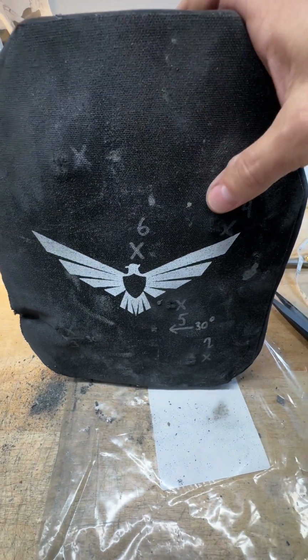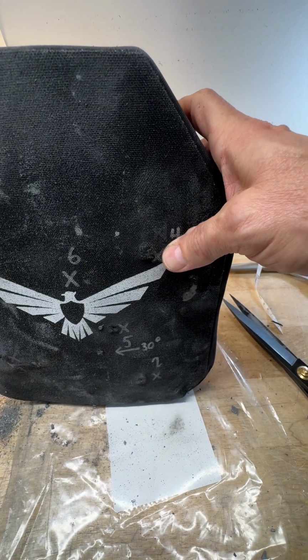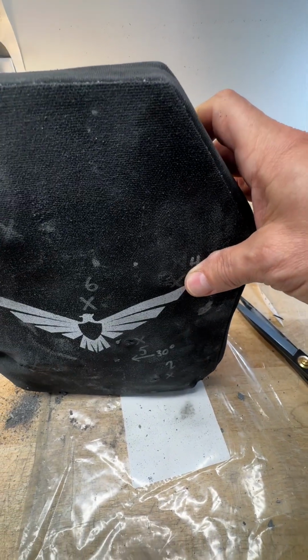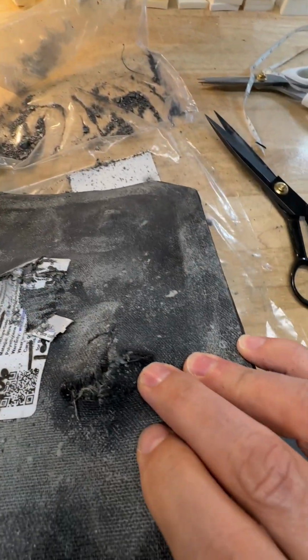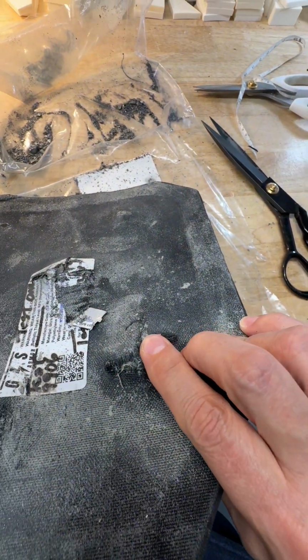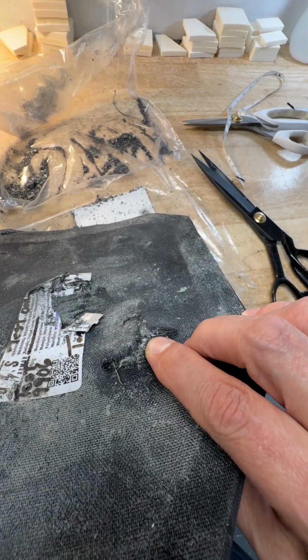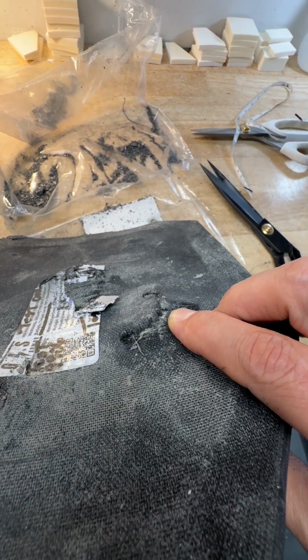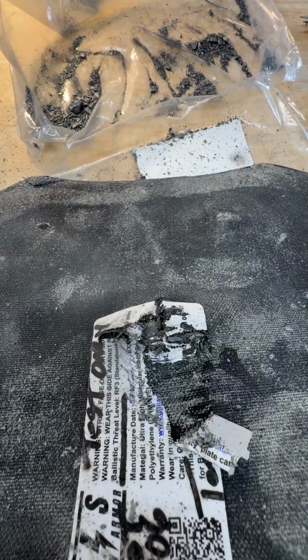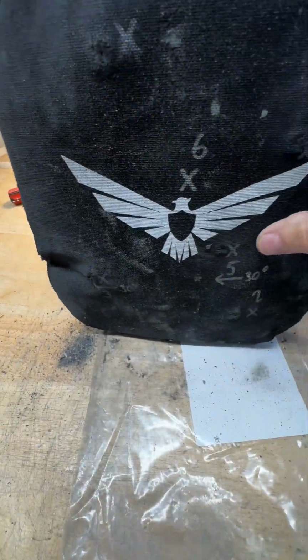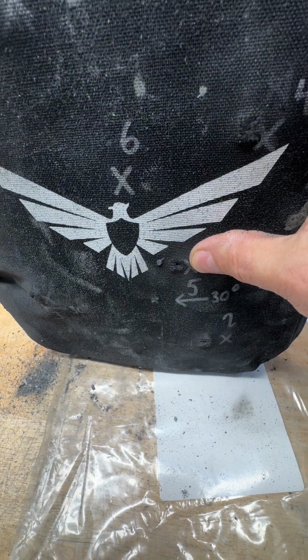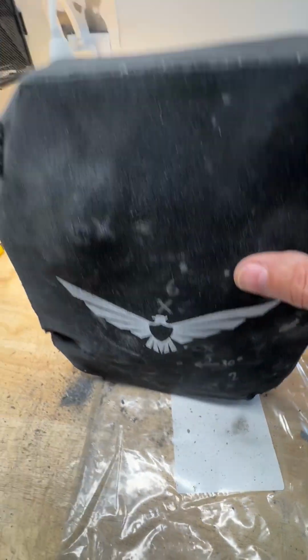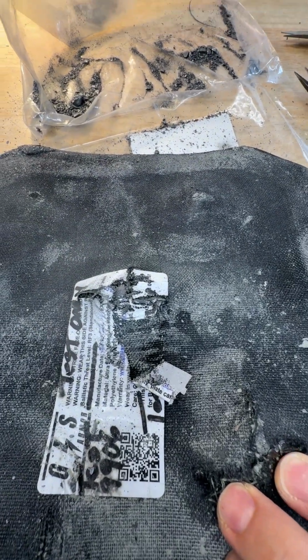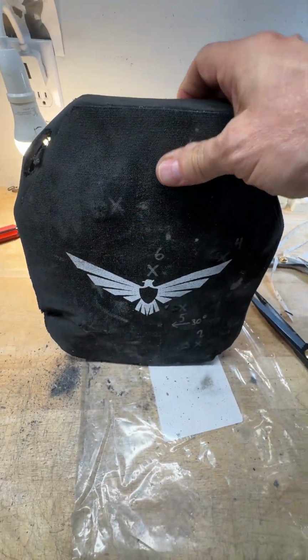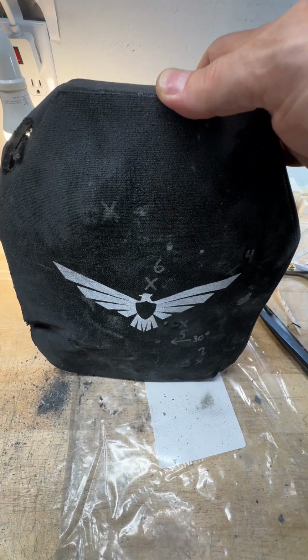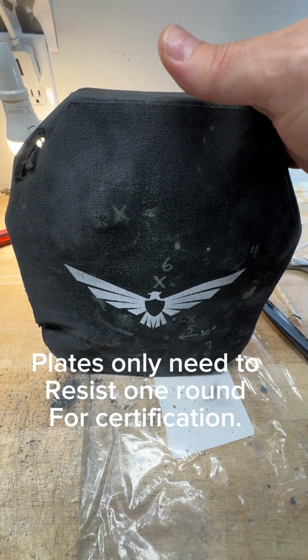Shot 4 was over here, and this is the first shot that actually exceeded the 44 millimeter maximum with the NIJ, exceeded it slightly here. This cracking you get is the result of the bending and cracking of the trauma reducer layer. Shot 5 went through right there, and this is shot 5 down in between these two, 2 and 4. So shot 5 did go through, but this plate resisted the penetration of 4 .30 caliber M2 AP rounds.